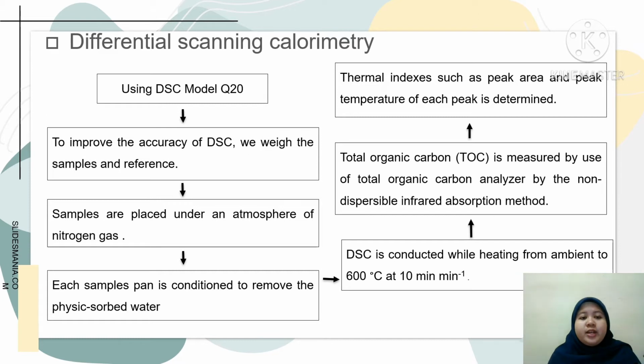Okay, to improve the accuracy of DSC, we weigh the samples and reference to ensure that the difference between both sample and reference is less than 0.1 mg. Next, samples are placed into a standard aluminum pan under an atmosphere of nitrogen gas. After that, each sample pan is conditioned to remove the physisorbed water. DSC is conducted while heating from ambient to 600 degrees at 10 degrees per minute.